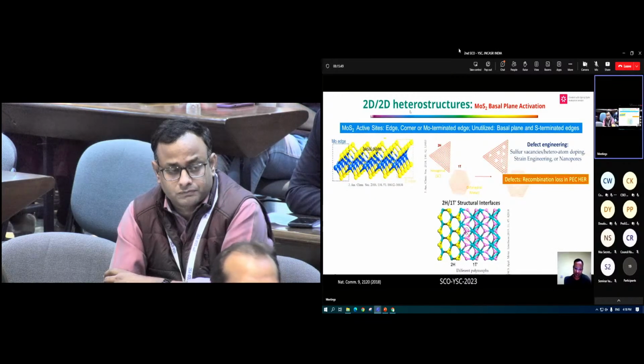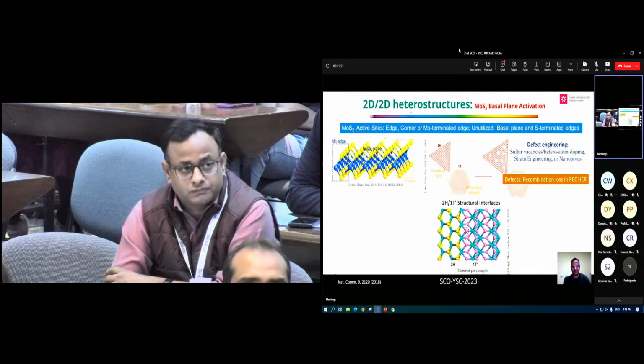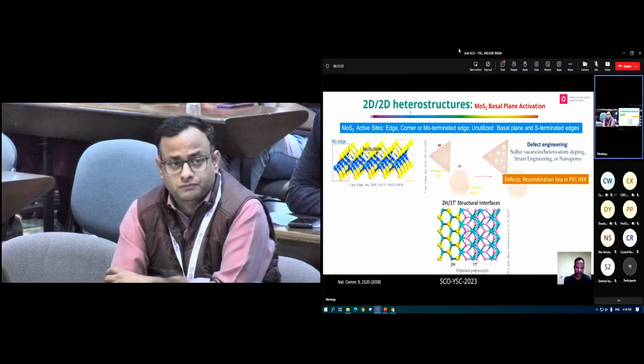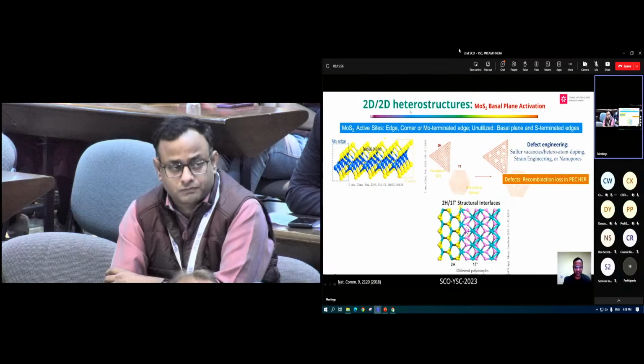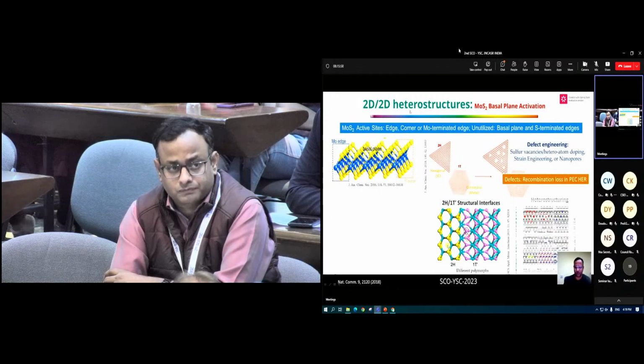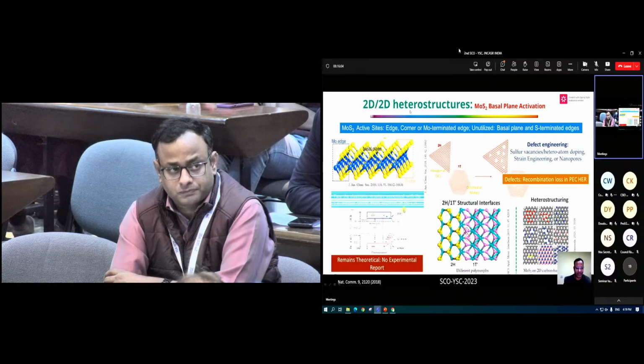The other solution that has been projected is using the 1T phase, which is the metallic phase. Once you use the 1T phase, it becomes metallic, and that is also not a solution for photoelectrochemistry. Heterostructuring can be a solution, but it is mostly reported in theory. So if I summarize, the work has been reported mostly for valence band electrochemistry, but once you excite the electron to the conduction band, there is no report on how to activate the basal plane. So we have worked on that.